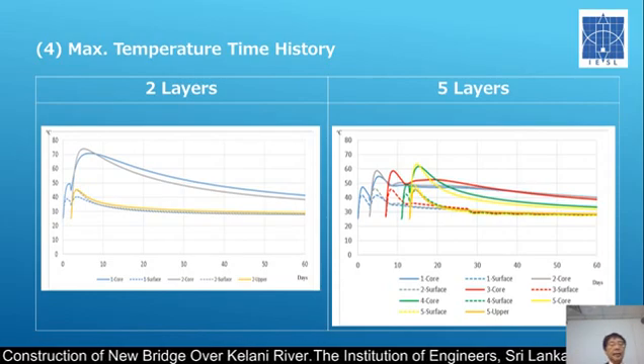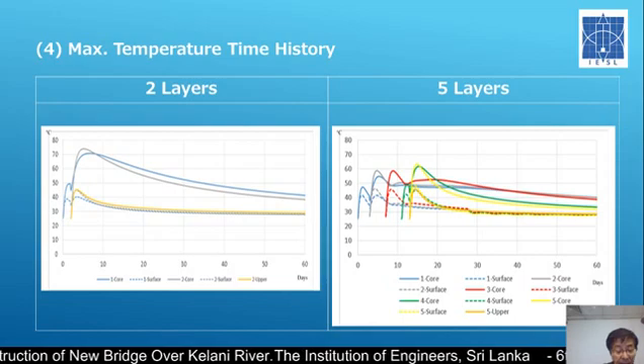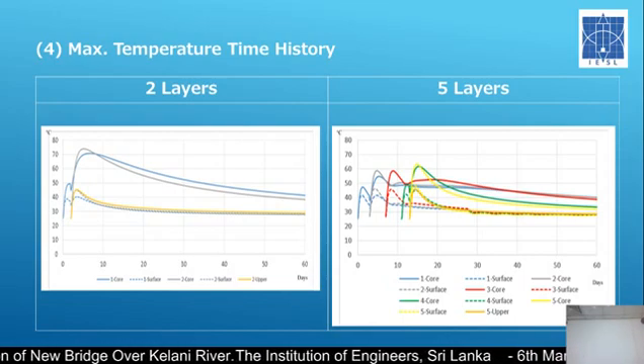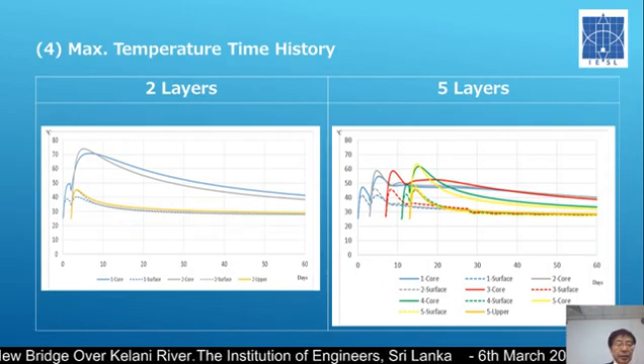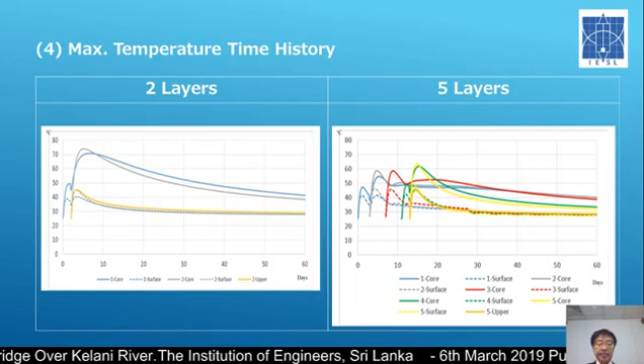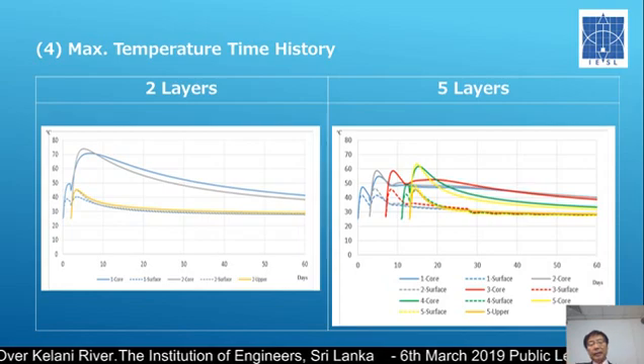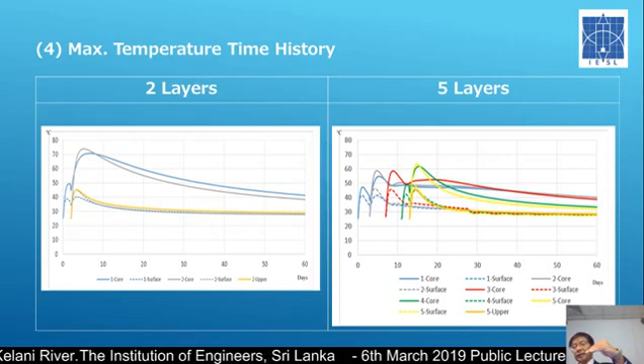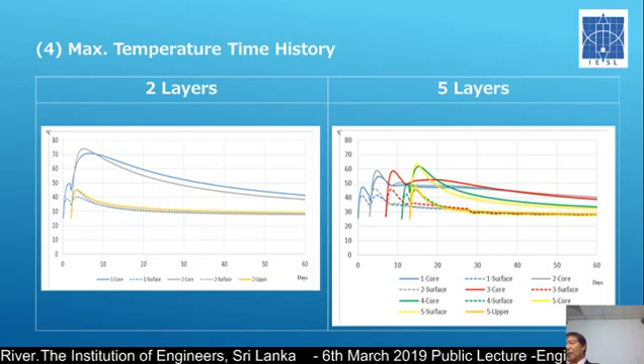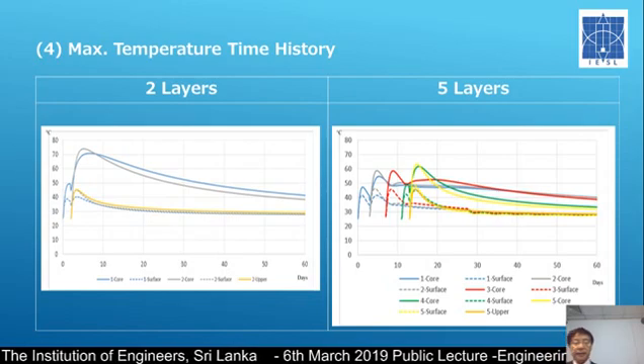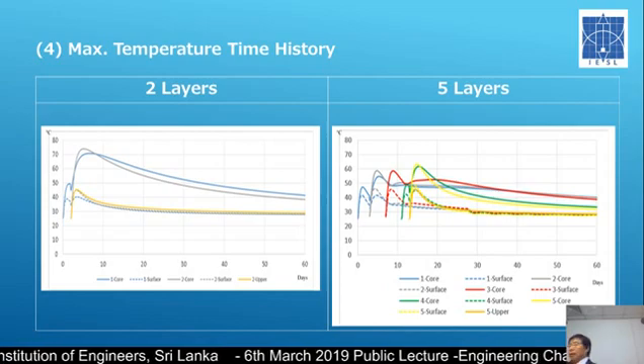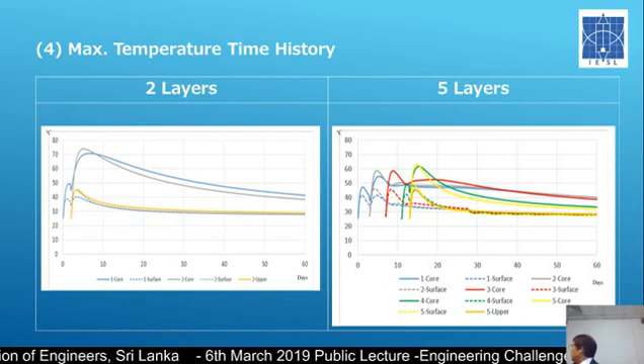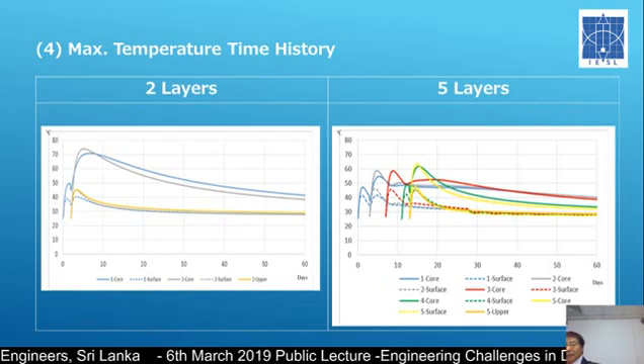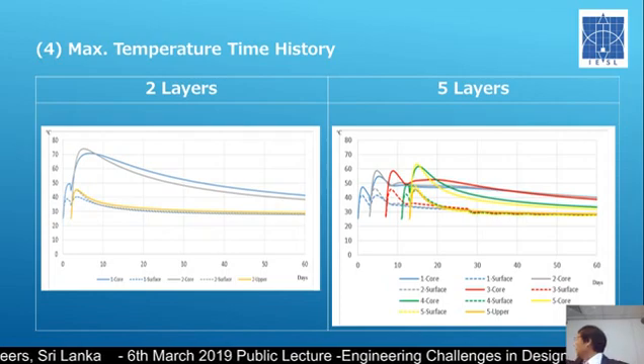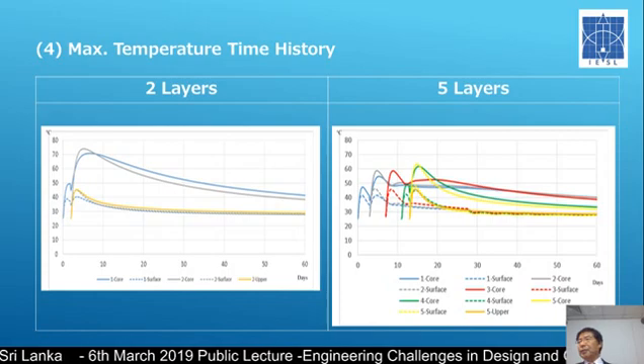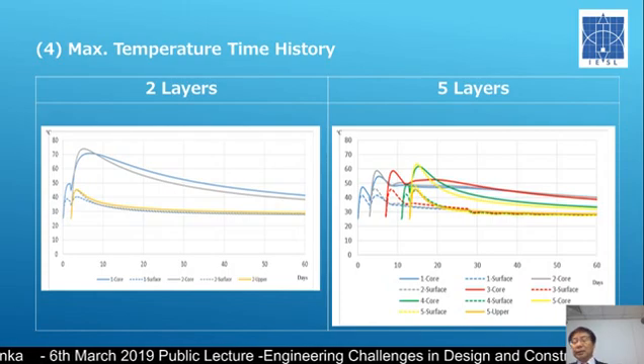So this is a history diagram of the temperature. On the left-hand side, you can see the two top, first layer and second layer, which go close to 72 degrees. So the first layer is cast, and after 3 or 4 days, the first layer concrete temperature lowers. Then the second one is added, and that gives heat to the first layer. In the same way, with 5 layers, you can see interesting curves: the first layer is going down, and when the second one is added, it goes up. And then finally, 10 days or 20 days later, the entire concrete temperature is lowering. So this is the accumulation of heat, the interaction of the heat between the layers.